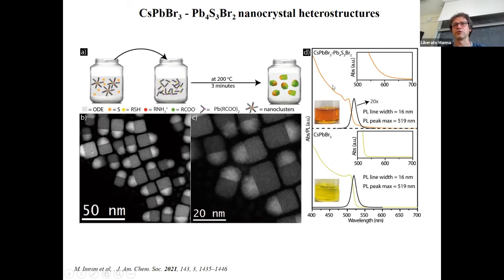The optical absorption features of these chalcohalides look very similar to those of the perovskite. In addition, there is the tail due to the chalcohalide. The residual PL, very weak PL coming from this sample, is most likely just due to residual isolated nanocrystals of perovskite, because in reality what we have seen and been able to demonstrate is that when you grow these heterostructures, you completely quench the PL from the perovskite domain. Okay, now what can be done with this?